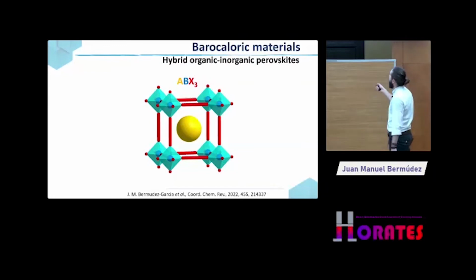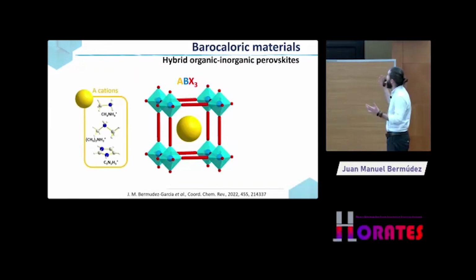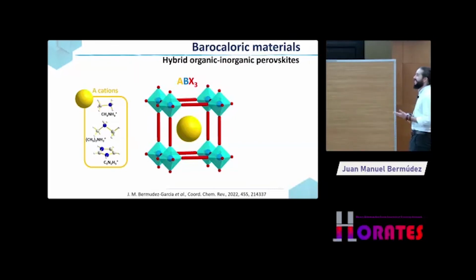So you have in the corner BX6 octahedra, and in the middle you have pseudo-cuboctahedral cavities where you can put different cations. In the general case of hybrid perovskites, in the A position in those cavities, you can put mid-sized alkyl ammonium cations, for example, methyl ammonium, dimethyl ammonium, imidazolium, and so on. In the B position, you can put transition metal cations.